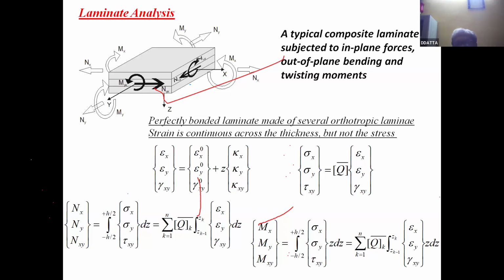Those who have studied, they know very well. And here the concept is the strain components at any layer measured with respect to geometric mid surface, that is mid-plane strain plus z times kappa. Kappa is the plate curvature. And this can be related: sigma x, sigma y, tau xy is related to epsilon by virtue of Q bar. We have discussed about Q bar. And the loads and the moments, they are related by this equation.